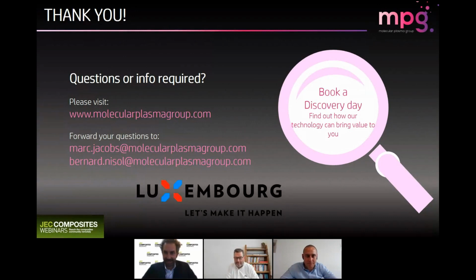Thank you, Mark. Next question from Claude Mack. When treating fiber rovings, are you assuring that the fibers in the middle are also treated? Bernard? Well, in the middle, there is a possible penetration in porosities up to microns in materials. If you're lower than that, of course, you cannot be sure that the activated molecules and the active species from the plasma will actually efficiently penetrate the material. So to some extent, yes, but there will indeed be limitation to that. And of course, there will obviously be a gradient. What is in the outer region of the material you treat will be more treated than the inner range. Up to a micrometric porosity, it's possible. If you're below that, then I have doubts, to be honest.